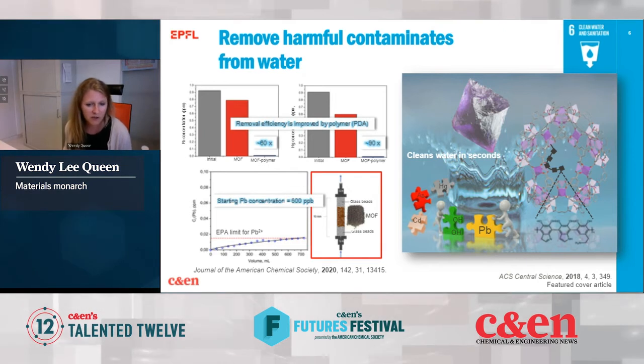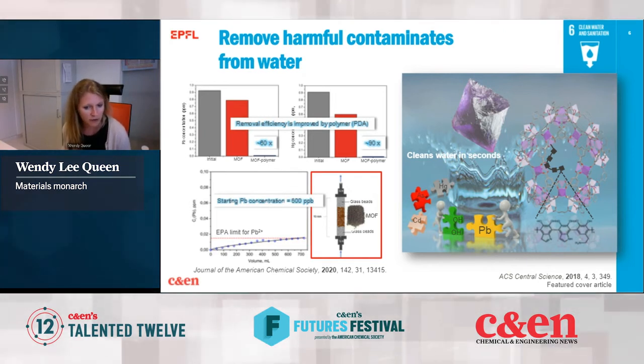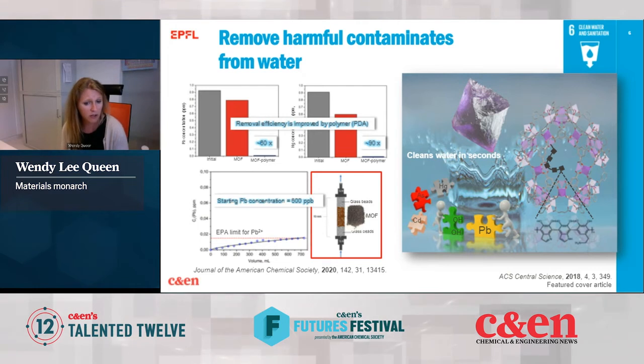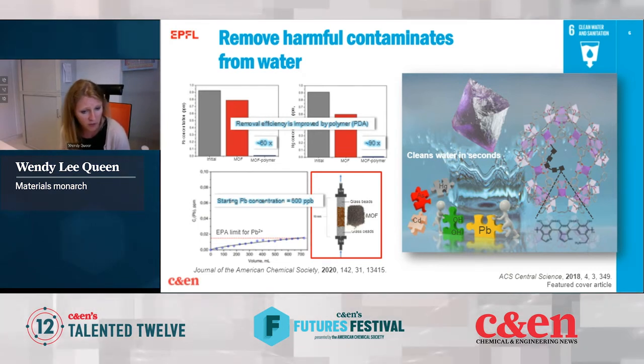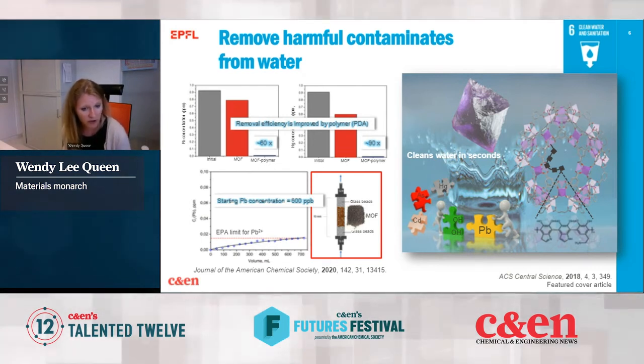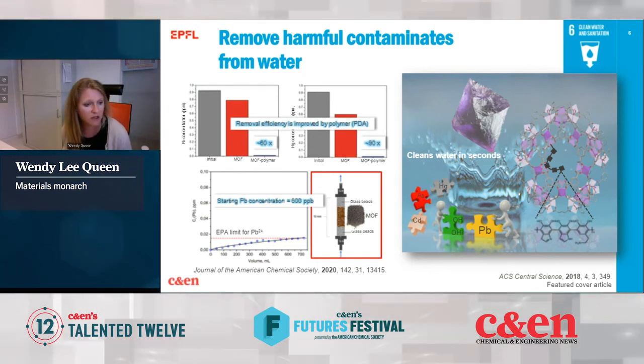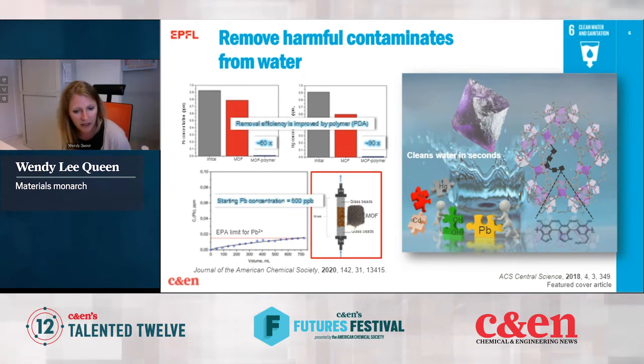So we form these little MOF beads. We flow contaminated water through those. So here you can see the starting concentration of lead, 600 parts per billion. We note that when we flow it through, we're well below the EPA limit. It's about 15 ppb, which is what is deemed drinkable by the EPA.